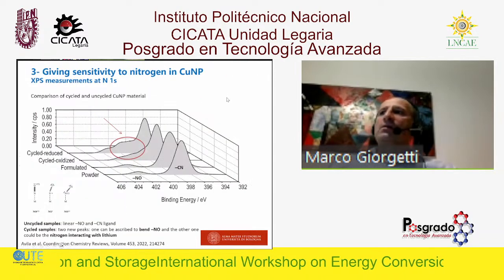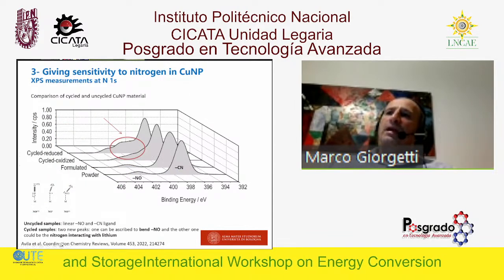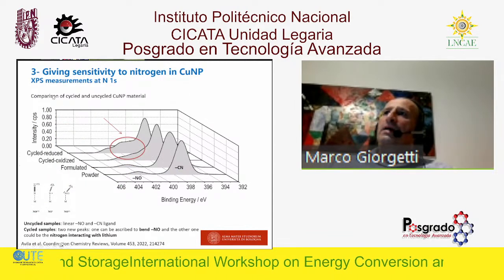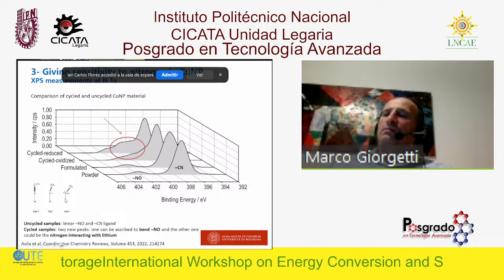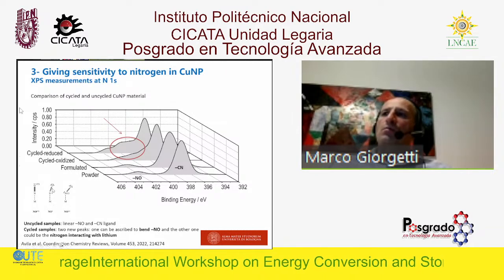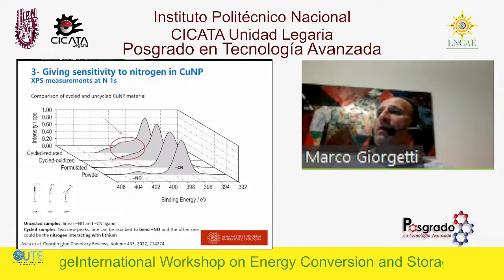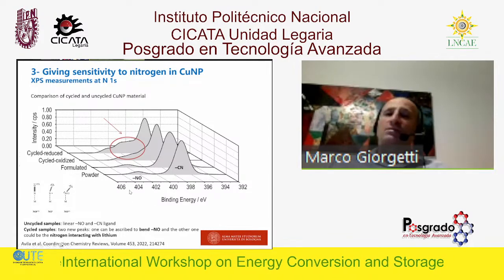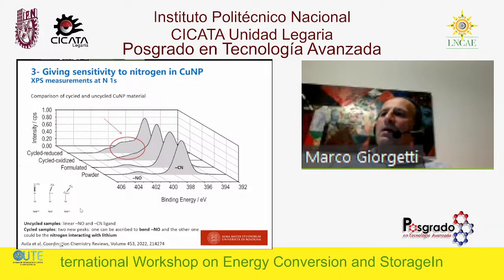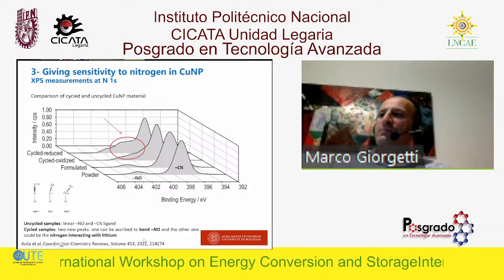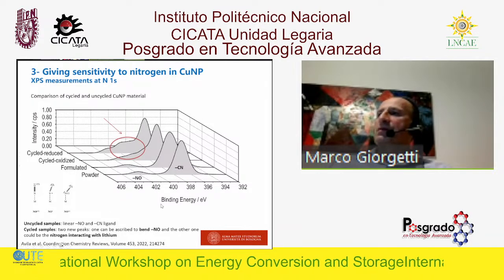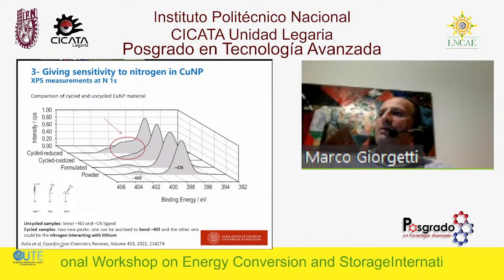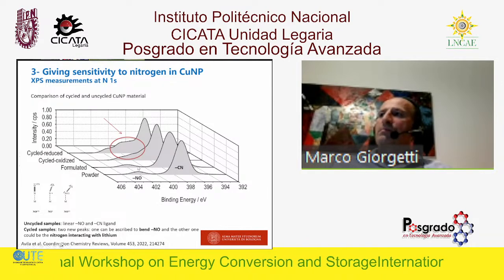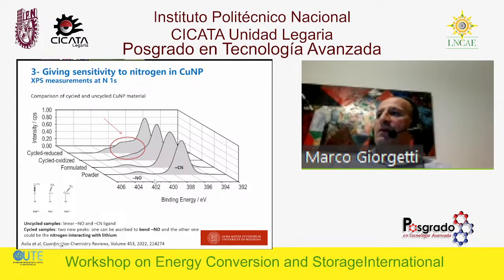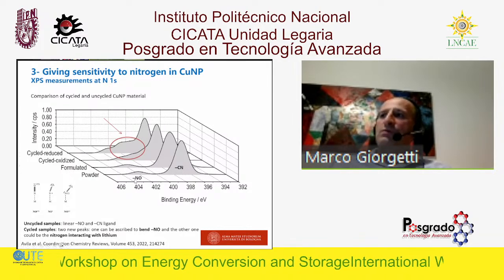The only way in which we could measure the electroactivity of NO was by an XPS experiment. And so this is the metal NO. We know that during oxidation, so the charge, we have a bend of this NO. And one of the ways was just looking at the binding energy, so an XPS experiment. Actually, here, some of your papers helped us a lot, because if you consider the powder, this is the formulated electrode. So this is the single powder, this is the electrode. It's very clear that we have two contributions, one to the CN and one to the NO.